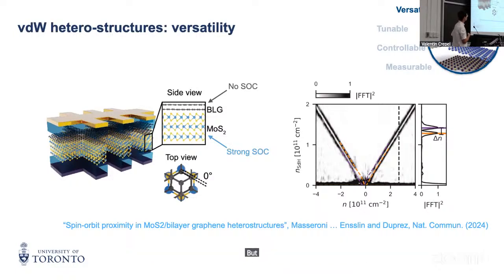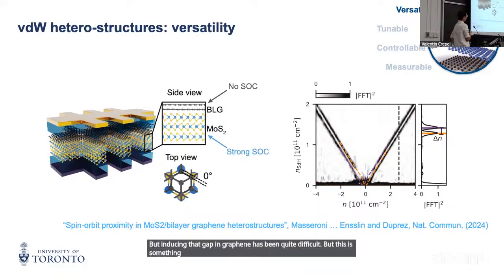But inducing that gap in graphene has been quite difficult. But this is something that you can do by just adding below graphene a monolayer that has a strong spin-orbit coupling, that can induce on the bilayer graphene some spin-orbit coupling and open the gap of graphene, as you can see in the splitting here. And so that's just one typical example of what you can do if you are not bound to have any chemical bonds between the two layers.